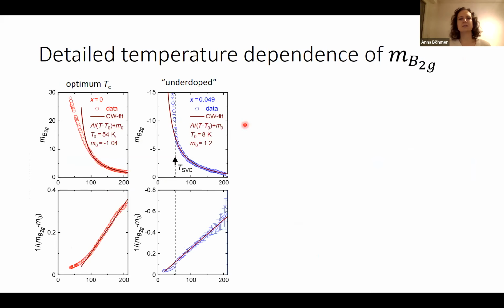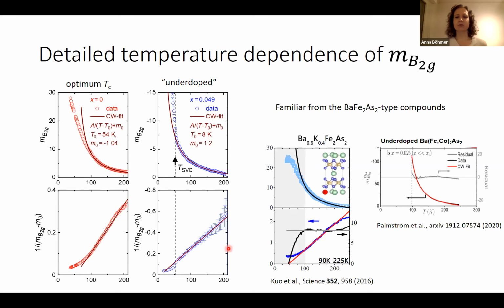And as is customary in the field, I tried a Curie-Weiss fit. For the optimum TC sample, the undoped 1144, the Curie-Weiss is approximately working, but there are strong deviations, especially at low temperature. For the nickel-doped one, which would correspond to an underdoped 122, there's a beautiful Curie-Weiss law. That works very well. So again, this is reminiscent and familiar from what we know of the 122 compounds. This optimally hole-doped barium 122 looks very similar to this optimum TC 1144, even in the way it deviates, while the underdoped 122s show a very nice Curie-Weiss law down to their transition, same as here. So this is very, very familiar behavior.